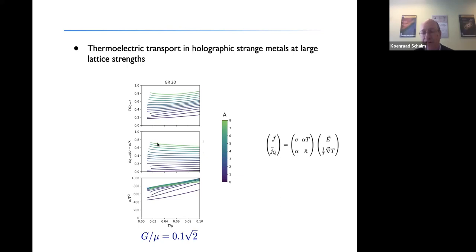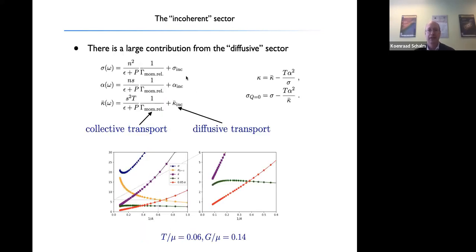And this is precisely what is expected, because based on this Drude model, remember that there was this Drude part which was proportional to the inverse momentum relaxation rate plus this incoherent term. As you increase the lattice potential A, of course, the momentum relaxation rate goes up, and therefore its contribution should go down. And so the contributions to the conductivities should start to become dominated by this incoherent part. And that's precisely what you see in these systems. There's a large contribution from the diffusive sector.